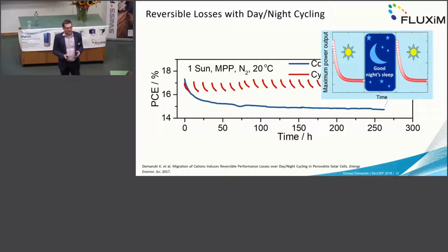And as it turns out, the cations that are mobile in this material can move on a long time scale of hours and accumulate at the interfaces and modify the efficiency. But then when you leave them in the dark, the device can fully recover.